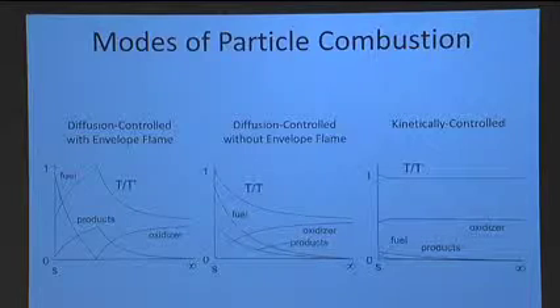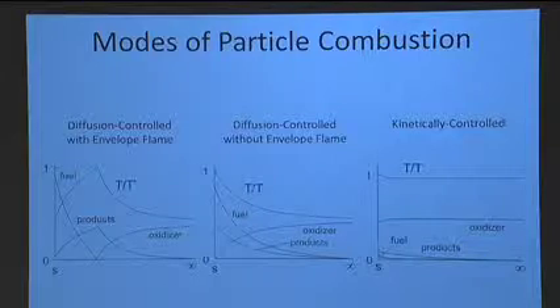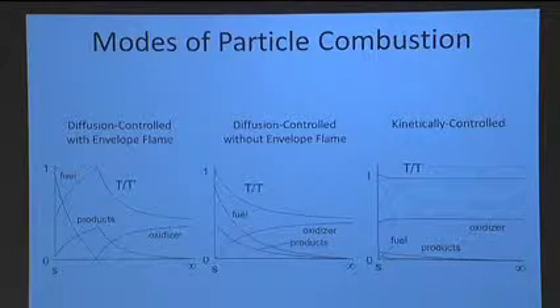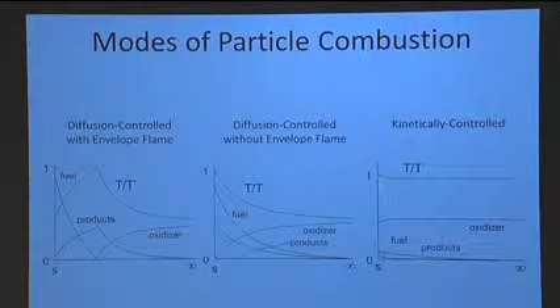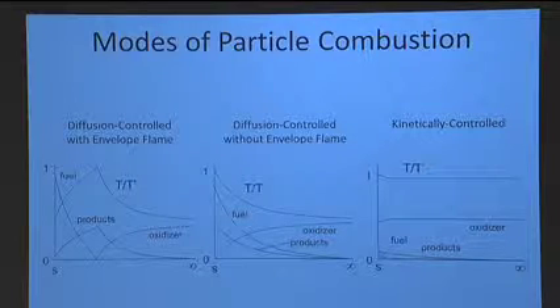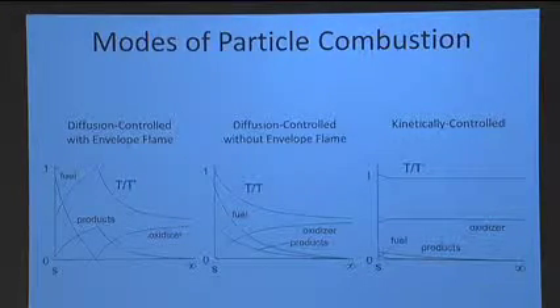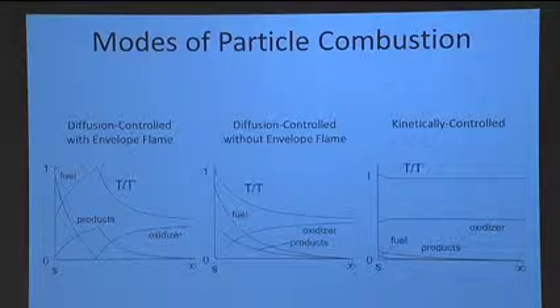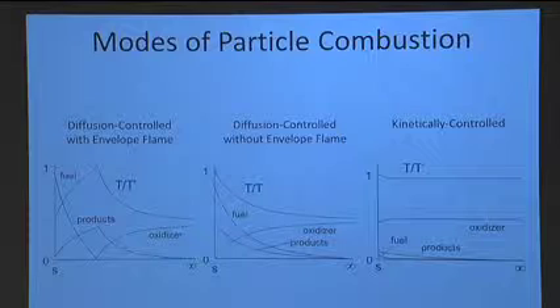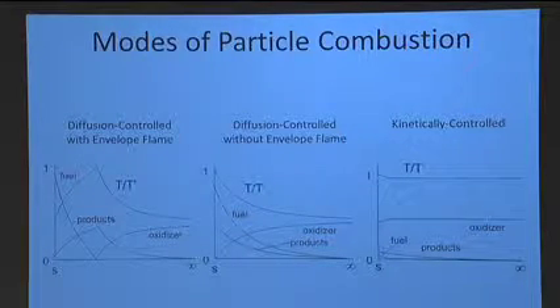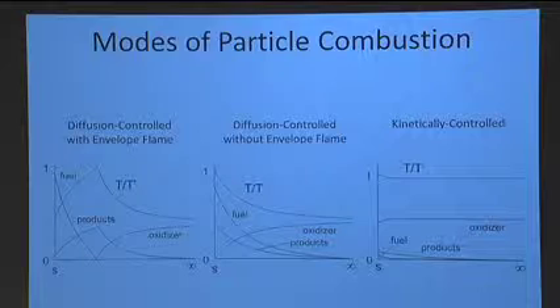Now, if I go to the other extreme where I start to basically slow the mass transport down, okay, what I end up with is a situation where I can no longer get rid of the gradients in the environment around it, and I start to see spatial gradients. And under these conditions, my transport is what's rate limiting, and I have what's referred to as a diffusion controlled process versus a kinetically controlled process. And I show two examples here. In this particular case, much like the aluminum particle that I showed you, I have a surrounding envelope flame. And so the fuel is leaving the surface, and I have oxidizer coming in, and it's these processes here that rate limit the process, and I have very fast chemistry when they come together, and I form a diffusion flame. Now, I don't have to have the gas reaction occurring in the surface. I could still have a diffusion controlled process on the surface, but I'd still end up having spatial gradients, and this process would still be diffusion controlled.